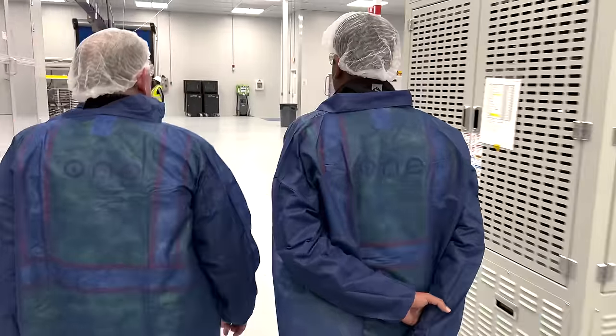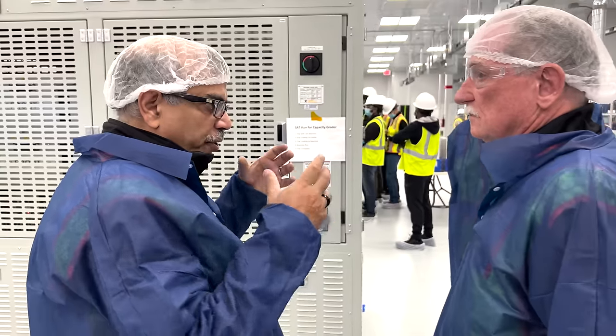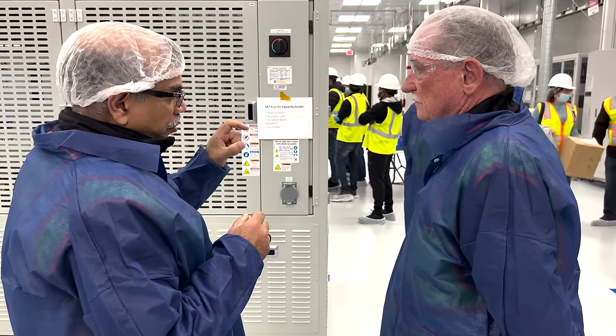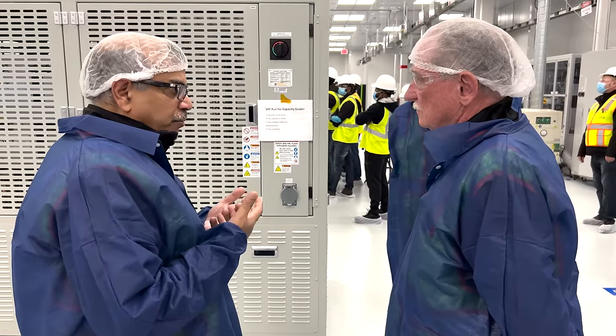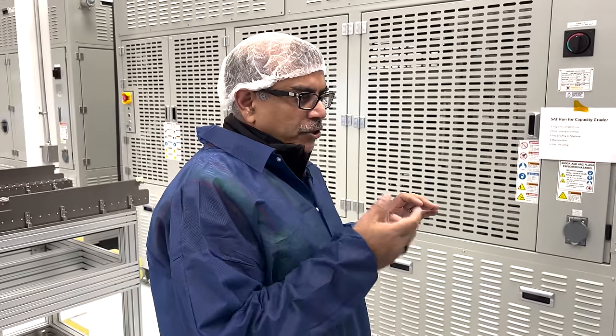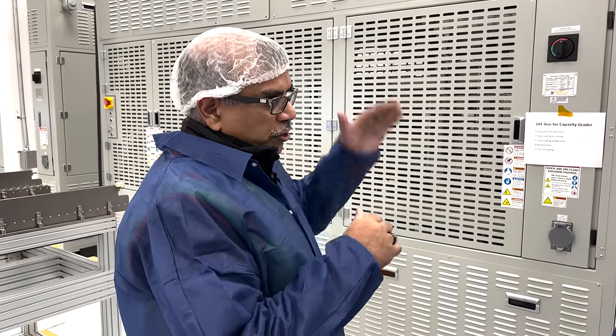These are the formations — this is kind of the birth charge. The very first charge the battery goes through after we put in electrolyte and it's fully degassed: we bring it over here, charge it — not all the way to the top. When we charge it a little, we go back and degas. Then we come back, weld it shut, and then we can charge and discharge. That first charge generates gas because all of the particles in the anode have to form a surface chemistry called SEI — solid electrolyte interface. Once we get rid of that gas after the first bit of charge, we weld it shut, then we can charge and discharge, measure capacity and quality, and it's ready to go.